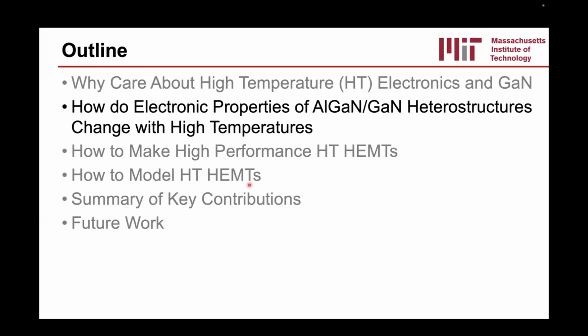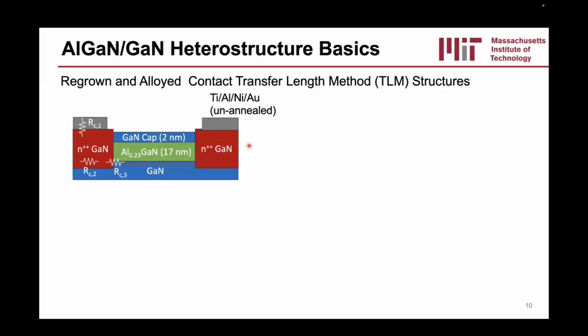Okay. All right, so now we can go on to the first research question that we have: what do the properties of these devices, or the AlGaN/GaN heterostructure specifically, look like at higher temperatures? To begin with, I'll start with a very basic AlGaN/GaN structure. It has a little bit of gallium nitride, and we grow some aluminum gallium nitride on top. Because of the polarization difference between these two materials, you get a really nice 2D electron gas, which is a sheet of electrons that's really conducting, that you can flow between two ohmic metal contacts and also modulate. And that's really the heart of our device.